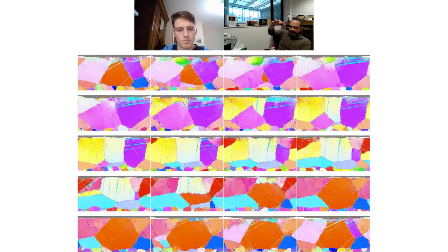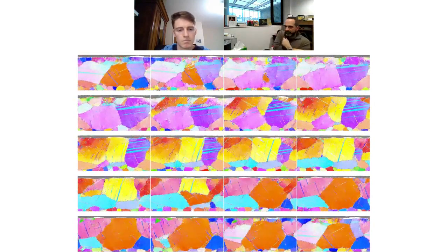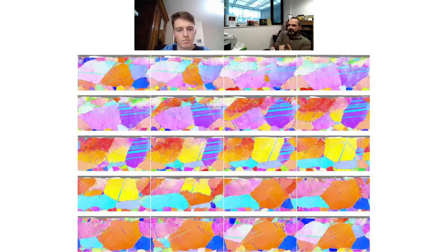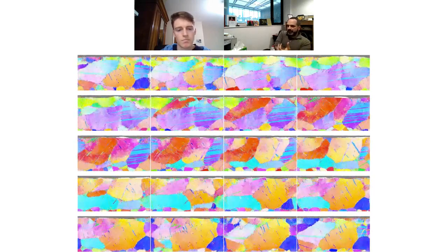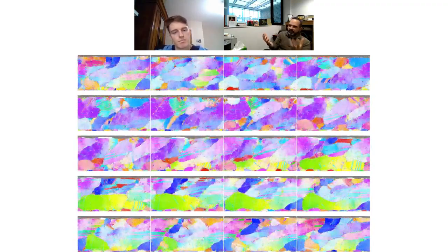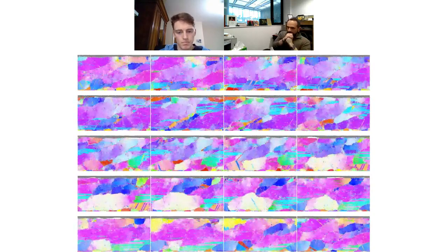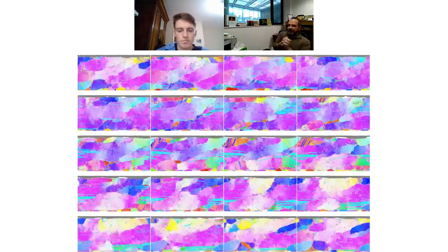So you press down, and as you increase the load, you'll see different things happening in terms of material transformation. Depending on the load you're applying and the composition of your material, in this case a binary alloy of copper and nickel, you will get different things happening. As you can see, if you increase the load to a certain point, you get severe damage.